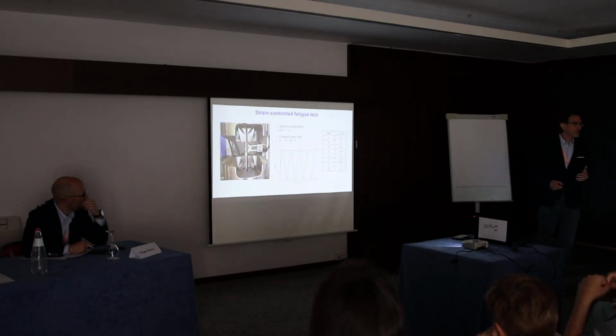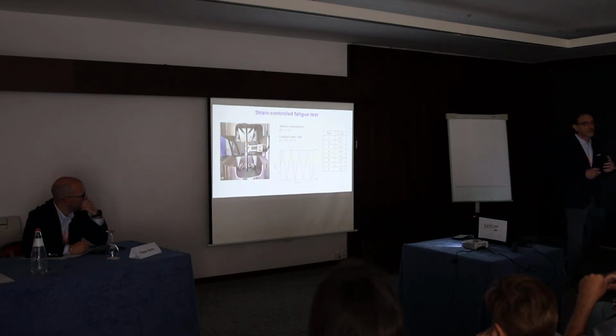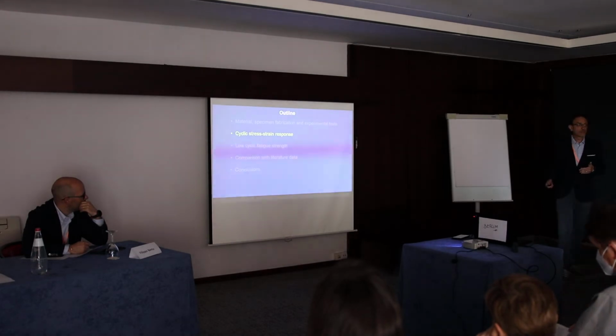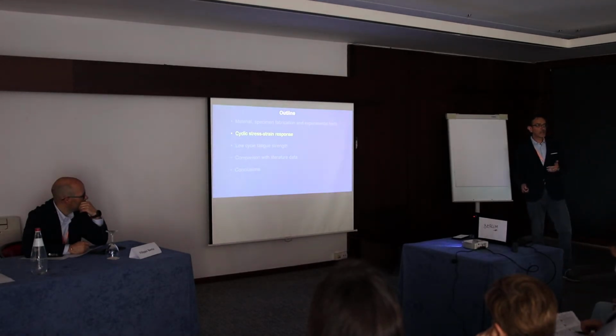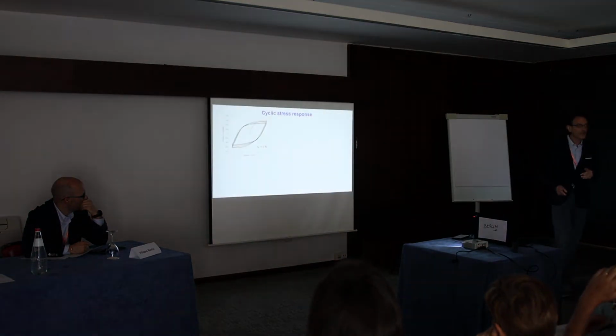Then we performed the tests. These are low cycle fatigue tests in push-pull condition, strain control, and in each test we monitor the maximum and minimum stress and also the entire stress-strain cycle at prescribed intervals. So now I want to show you some results, starting with the cyclic plasticity behavior.